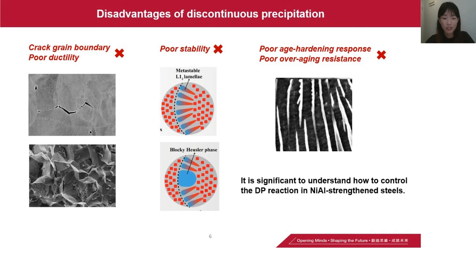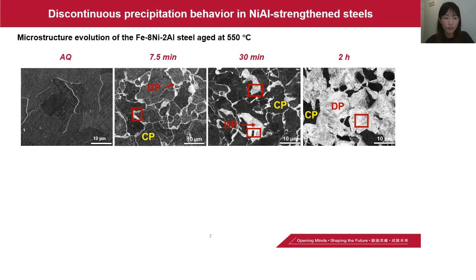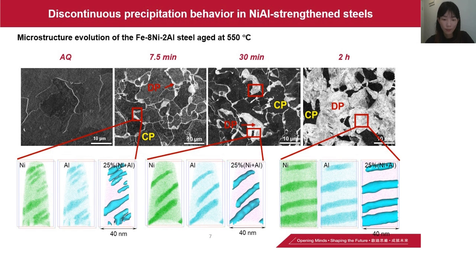In nickel-aluminum strengthened steel, how does the DP reaction proceed? We first check the microstructure evolution of our model steel. You can see from the SEM images, the bright contrast regions represent the DP region, while the dark contrast regions represent the CP region. With aging time, the area fraction of the DP regions increases significantly, reaching about 17% of the microstructure.